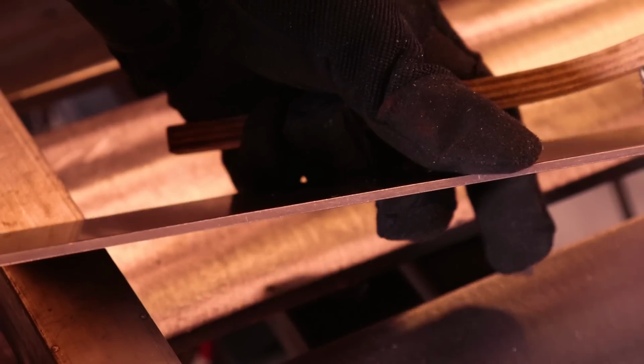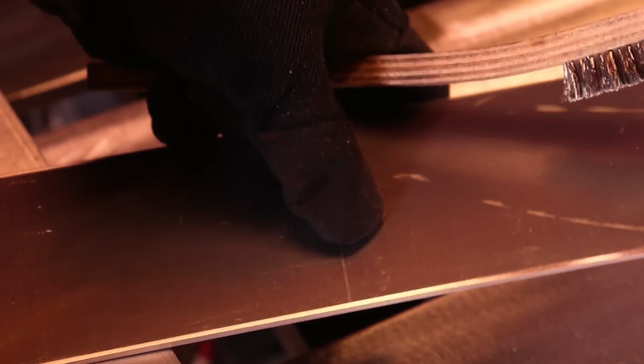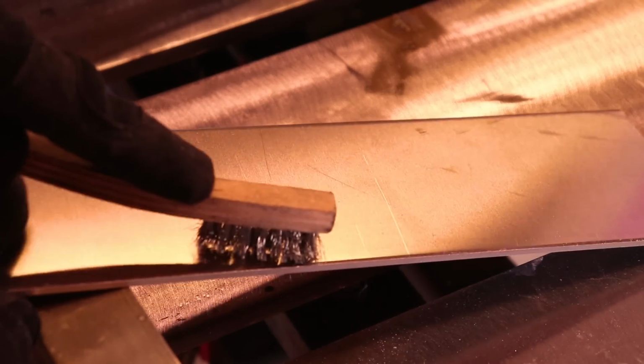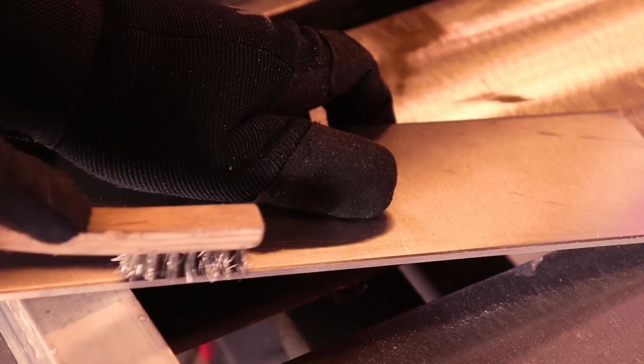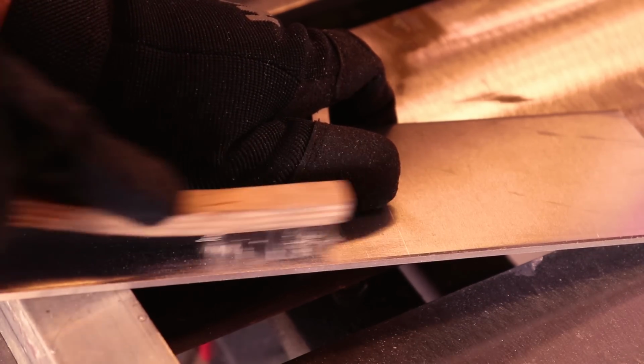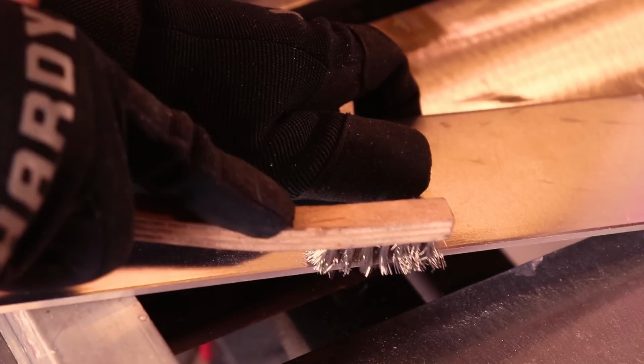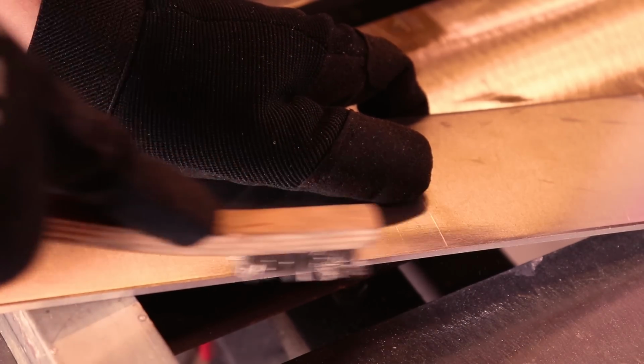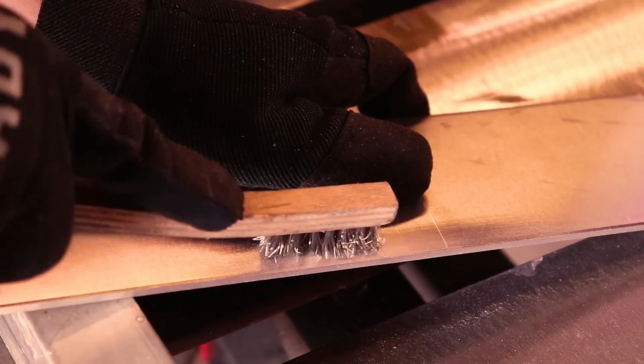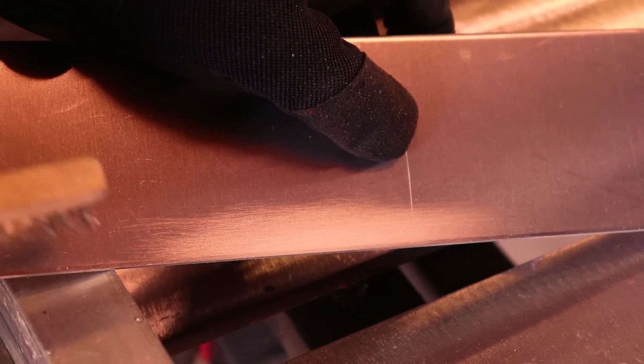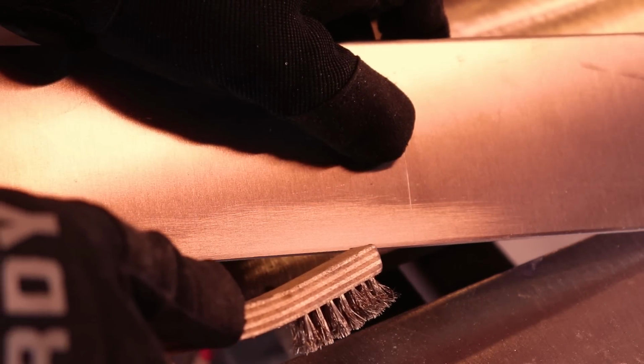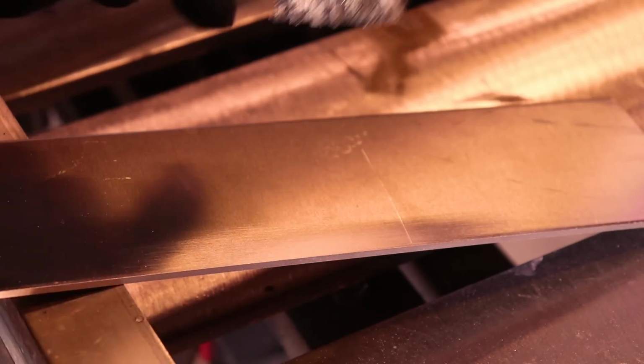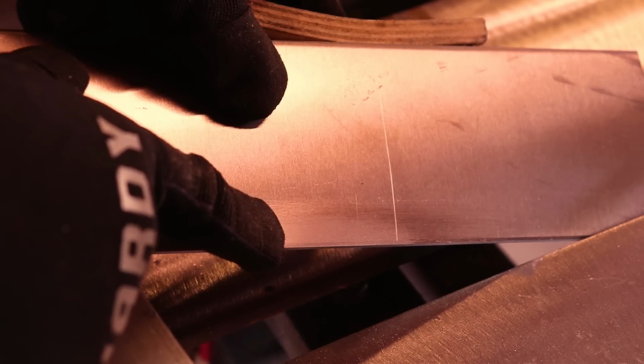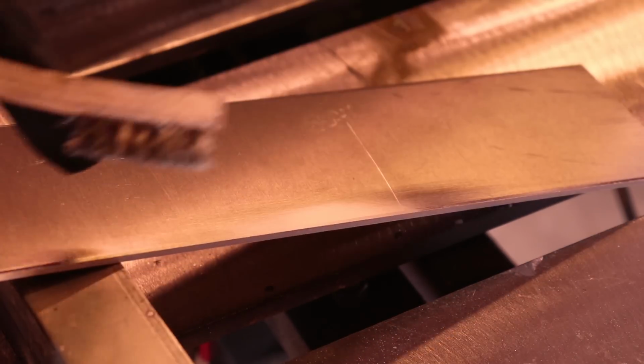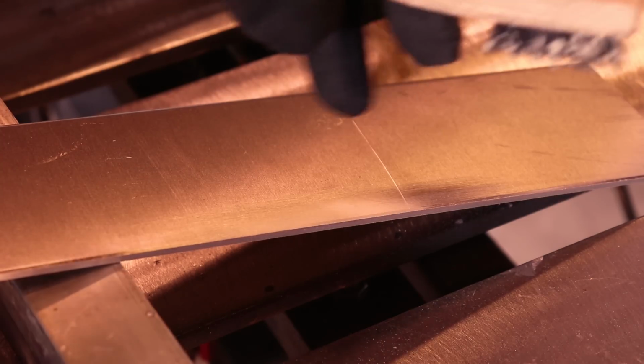Once I've got that whole edge done, then I turn it, and you're going to start, and you're just putting light pressure on it. And you'll feel it start to cut, like it's digging, and that means you've broken through that oxide layer. You can also see the color difference, and anywhere where you see the darker silver, that's where it hasn't broken through yet. So you can hit that from the side, and it'll clean that up like that. So then I just go through, do the whole thing front and back, especially if you're going to weld on the back side.